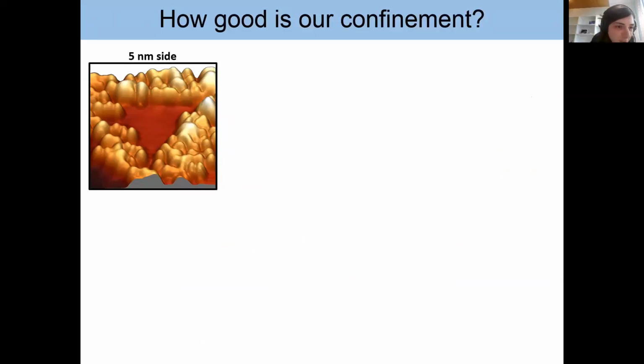Yeah. And then there's a third question, which is, why can't you cool the system down and repeat the measurements to get smaller broadening? Yeah, the problem here is you have thermal drift. Anytime you change the temperature of any material, the dimensions change. Our STM head is called a beetle-type head, and this is very well drift compensated, which allows us to keep the position very well even if you change the temperature. But usually when you change the temperature a couple of degrees, your tip tends to change position with respect to the surface, and then you completely lose everything. You have to be at a very good, stable temperature. Otherwise, the size of the material changes a bit, and then you lose position. The good thing of the beetle is that you can be very stable for many temperatures. The bad thing is that you cannot retract and approach, or you cannot move X, Y, and decide where you put your tip. So you have to have a compromise. It's really a huge challenge to change temperature and keep the same position in STM.